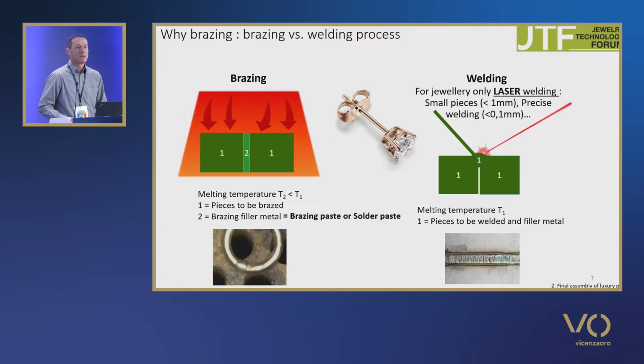For laser welding, laser ray melts locally the 2 different parts and creates a definitive link. For brazing, the key point is to insert a low melting alloy, not too low, and during heating, the low melting alloy creates a definitive link to assemble the 2 components.